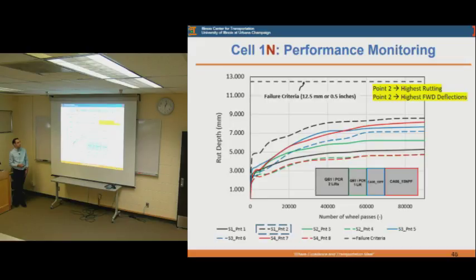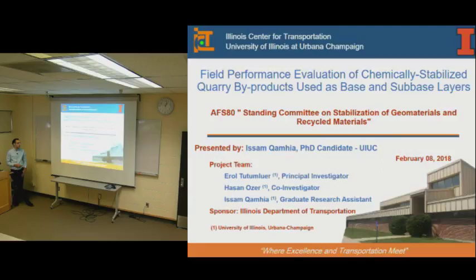So they were quite low compared to what was expected, which shows that all the test sections are working, and the applications that were investigated for the quarry byproducts in unbound layers were actually performing well even at a high number of cycles of 90,000 cycles in total. So this ends my TRB presentation about this topic.